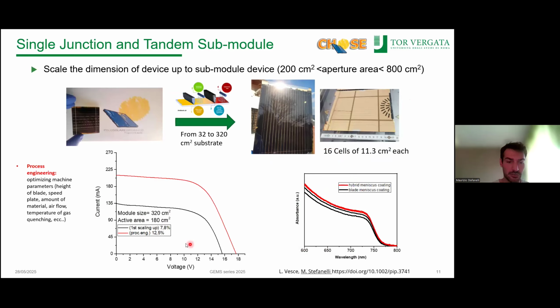So as you see, the first scaling up gave us quite poor module efficiency, just up to 7.8%, and then we started to process engineer, optimizing the machine parameters for the substrate size: height of the blade, speed of the plate, amount of material, the airflow, the temperature of the airflow, and so on and so forth. This kind of adjustment boosts the perovskite crystallization on the whole area and gave us the first jump of efficiency from 7.8 to 12.5%.